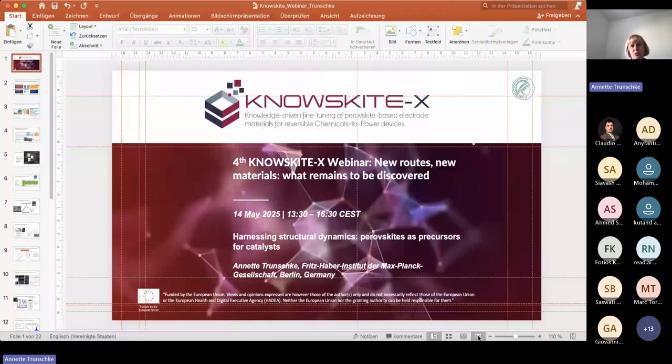And we also observed, I go back to this, very slow changes in the oxidation state. For example, here you see basically the same conditions as before, and you see a different manganese oxidation state. That means there are some solid state processes ongoing in addition to fast surface processes, which may also change the reactivity of our perovskite. In another study, we found also that the bulk of the perovskite is changing periodically with our reaction conditions.